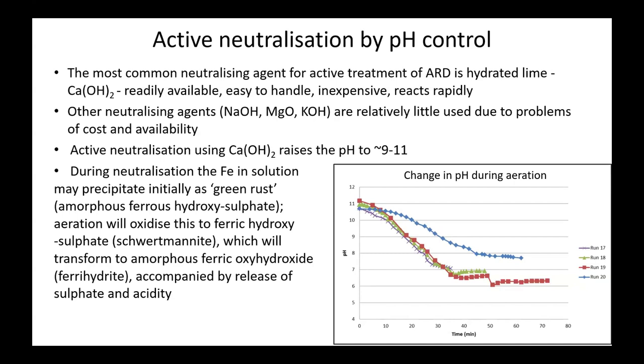There are lots of other neutralizing agents you can use, like sodium hydroxide, magnesium oxide, or potassium hydroxide. They're generally more expensive, or when they're not necessarily expensive, like magnesium oxide, in some cases, they're not available readily everywhere, only in particular places. Add calcium hydroxide, you can get the pH way up to 9 or 11, maybe. The equilibrium pH of calcium hydroxide is actually 12. So that's good. And so what happens when you add it?